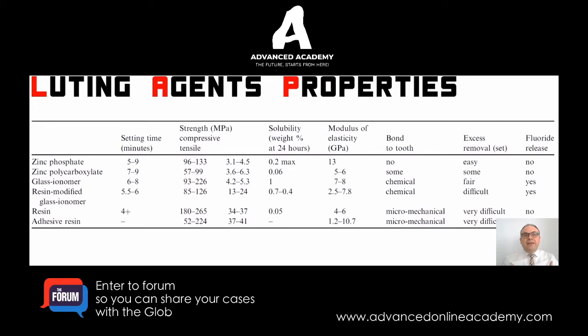The only way that these materials are successful in releasing fluoride is that you recharge them with fluoride constantly, and then they act as a reservoir to release fluoride. But that has to be done constantly with high concentrations of fluoride. So really, it is not a practical way of doing it. It's been proven and reported in research that any of the bioactive materials, any of the fluoride releasing materials, they're good initially, but then that property drops after a few hours to a day or two, and so really it renders useless in that sense.